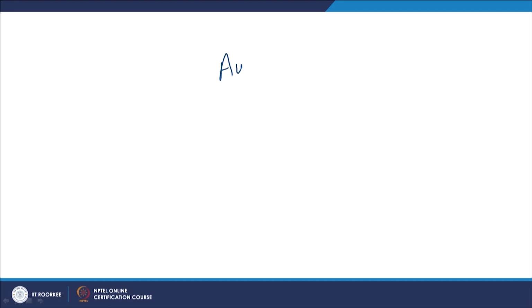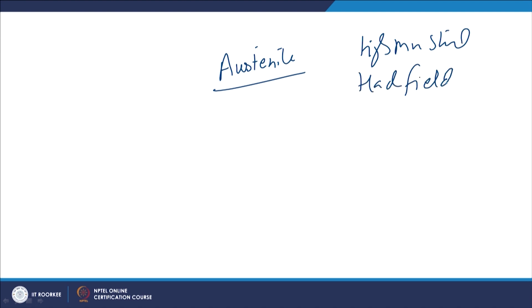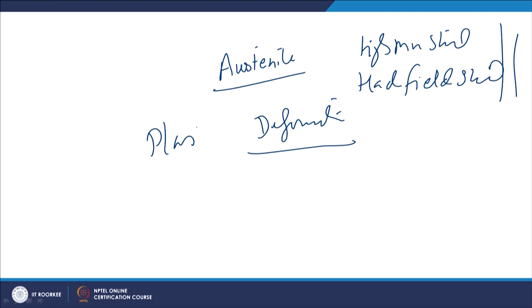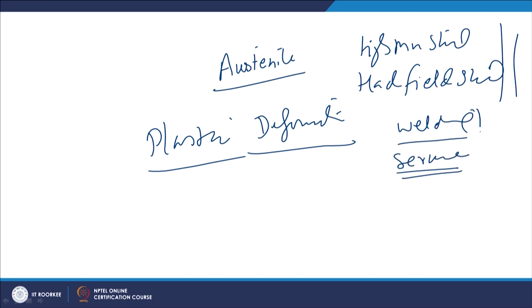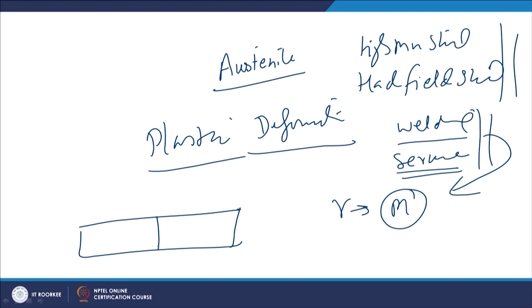There are a few categories of steels where the microstructure is primarily austenite at room temperature, like high manganese steels or Hadfield steels. When these steels are subjected to controlled plastic deformation, either during welding or during service, the austenite will transform into martensite. In these cases also, when they are subjected to welding through a plastic deformation based joining process, the controlled plastic deformation of the faying surfaces will lead to the transformation of austenite into martensite, and again we get a similar trend of variation in the hardness.